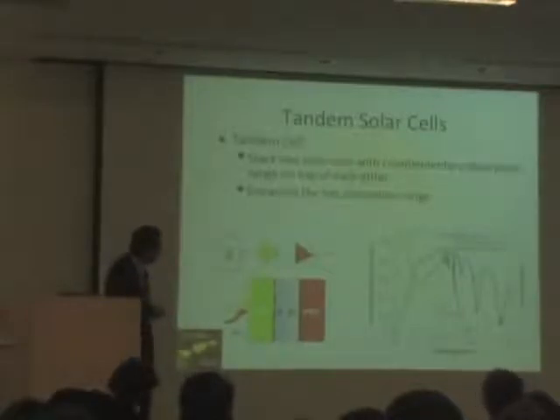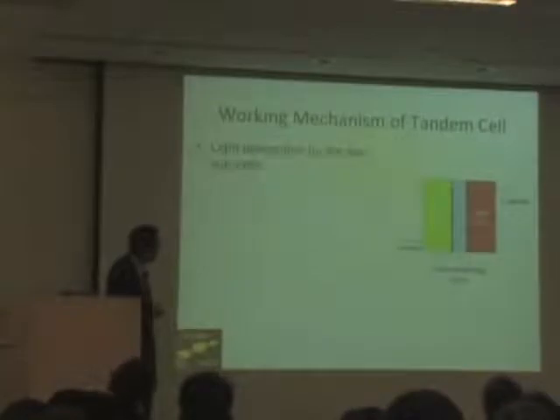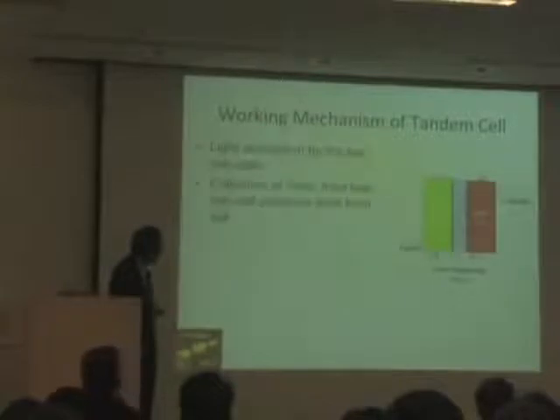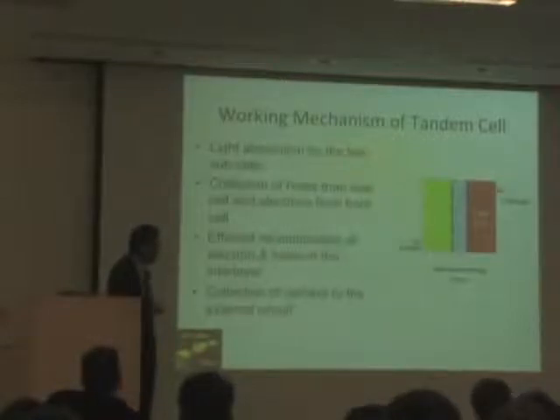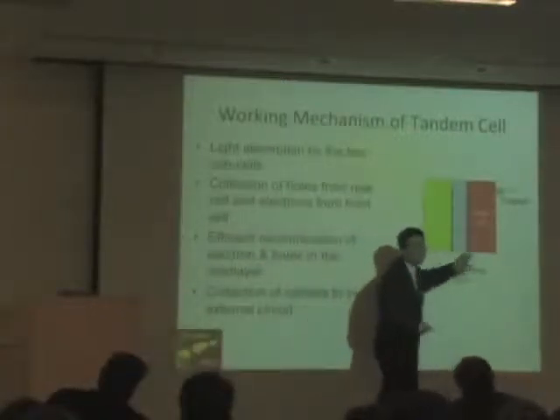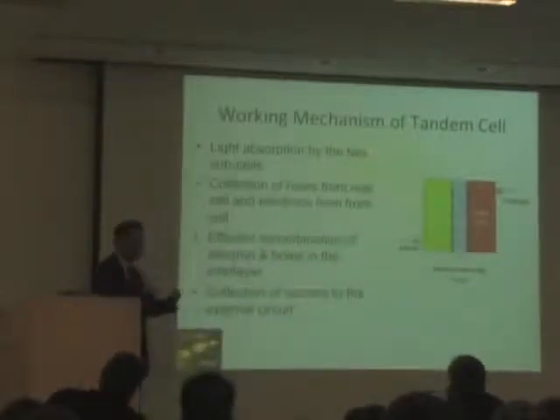So here's the working mechanism of the interconnecting layer. A photon comes in, and then the electron-hole pairs will go to the interconnecting layer, which is shown here, and recombine. And then the leftover electrons and holes will be collected by the electrodes. So the VOC will add up. The JSC will remain the same. So the key issue is to make the JSC, the short circuit current, identical in the front and rear cells, because you will go with the smaller one. You can make one cell extremely efficient and the other cell extremely inefficient. Unfortunately, you go with the inefficient one. So that's the key.